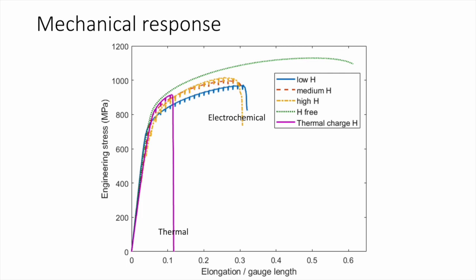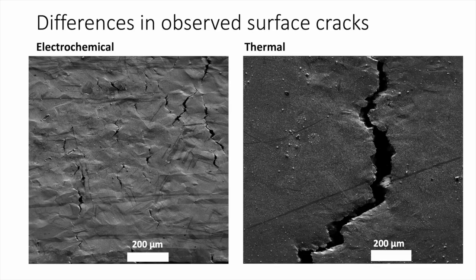Consistent with hydrogen embrittlement, we see the elongation to failure decreases with increasing hydrogen content. And these small intermittent stress drops in the figure correspond to the periodic pauses for the acquisition of the SEM images. You see the electrochemical ones are all grouped here, but the thermal one has more reductions. In the meantime, we compared the surface of the electrochemical charged one with the thermal charged one, and you can actually see it is quite different.